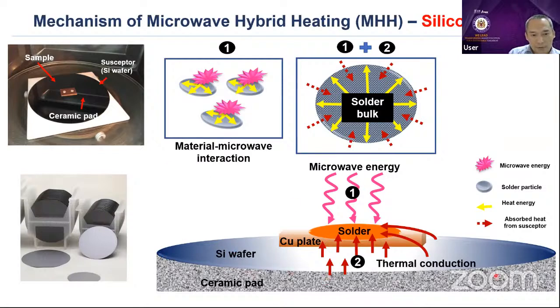So this one is the silicon wafer. This one is the ceramic pad, silicon wafers, copper plate, and the solder. This one is our sample, right? Okay, by combine two heating systems directly from the microwave, and then the heating actually starting directly from the microwave, but they start to heat the silicon wafers, and then the heat from the silicon wafer move again to the sample. Means that we have two types of the heating, directly and from the susceptor. And for sure, this one is more than enough to do the reflow. And combination of this type of heatings, that's why we call this one as the hybrid heatings.